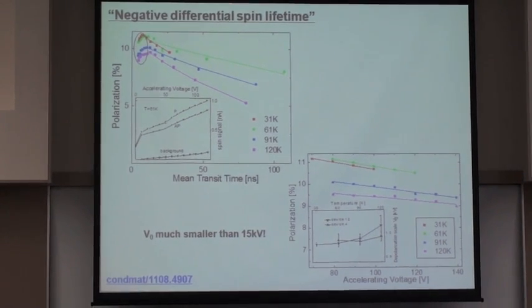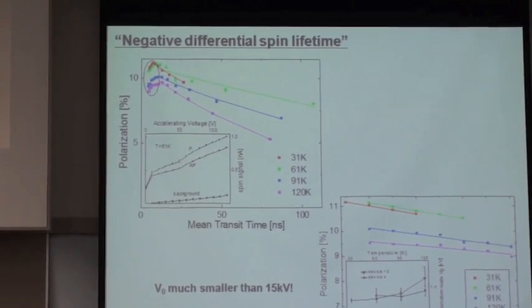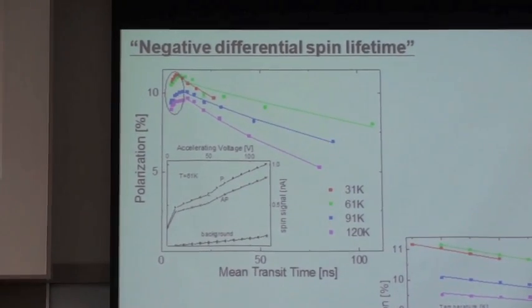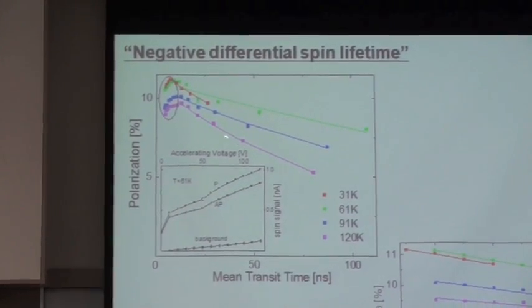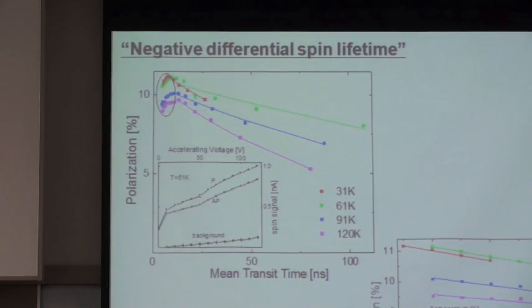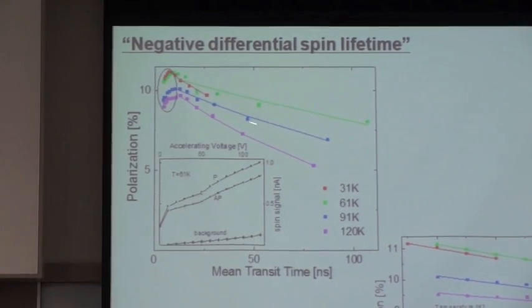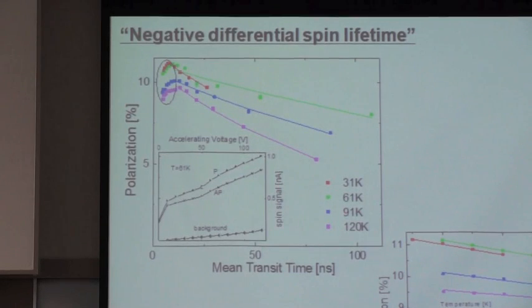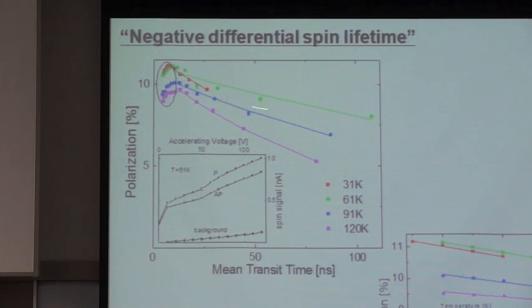So here once again is a measurement of spin polarization as a function of transit time determined by spin precession measurements. And you can see here for the low electric field case, which corresponds to a long transit time regime, we can fit this with an exponential. This is a linear scale, so everything looks fine. So this is the fit of exponential decay with some reasonable spin lifetime, several hundred nanoseconds or so. But as I increase the electric field more and more, I do get a shorter transit time, but the polarization actually drops. And it drops no matter what lattice temperature I'm talking about.